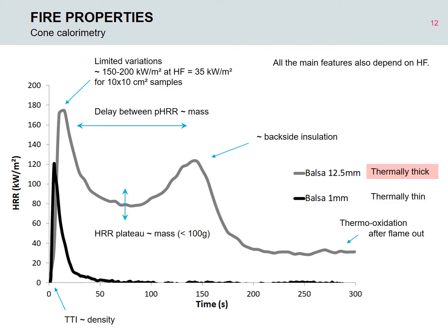At bench scale, in cone calorimeter, the typical heat release rate curve is the following one. Here it is the example of balsa, but it's the same for other woods. There is a first peak of heat release rate, followed by a plateau, a second peak of heat release rate, and finally at the end of the test, after flame out, we can observe thermo-oxidation. The first peak of heat release rate does not change very much according to the wood species. Its value is around 150 to 200 kilowatt per square meter for heat flux at 35 kilowatt per square meter.